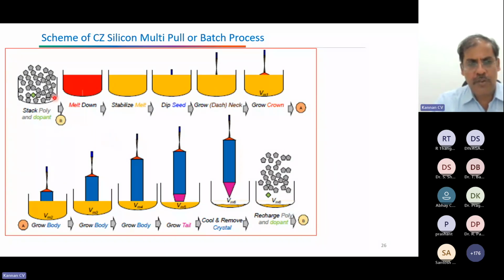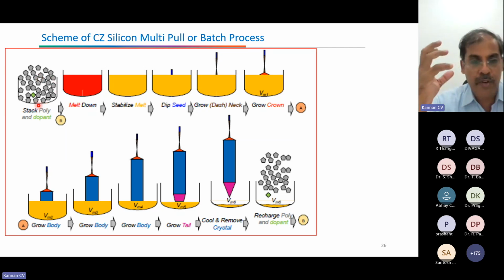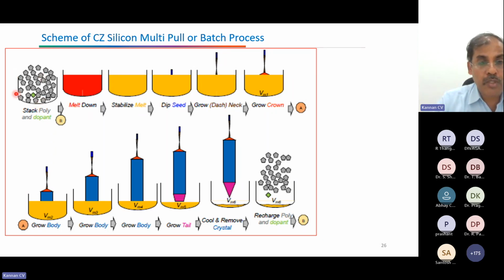So this is the process. It starts from the crucible, and we use high purity polysilicon. As I said, very high pure 9N, 10N purity polysilicon we should load into the crucible. And the crucible is a quartz material, very fragile, and it is the only material with less contamination that can withstand 1400, 1500 degrees. It becomes softened, but still you protect it with a susceptor so that the crucible will be intact. Then you melt it so that it becomes a melt, then stabilize the melt.